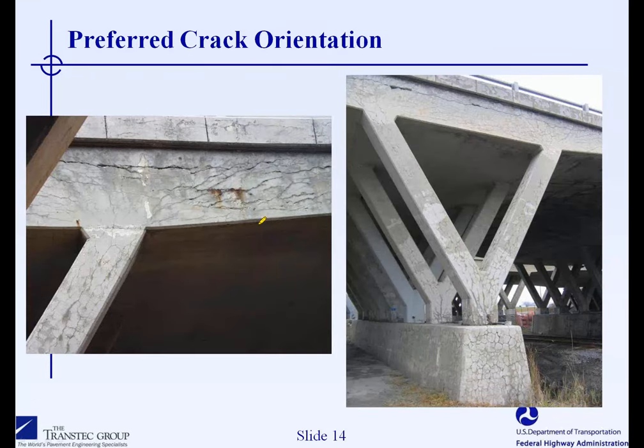This is an example of a bridge structure that was demolished about 2 years ago, close to my university in Quebec City in Canada. This structure was very, very badly affected by AAR and also other problems such as freeze-thaw and corrosion. We can nicely see the different patterns of cracking in the different elements of the structure. Some longitudinal cracks here in the bridge deck, also longitudinal cracks here in the concrete columns, pattern cracking in the foundation block.